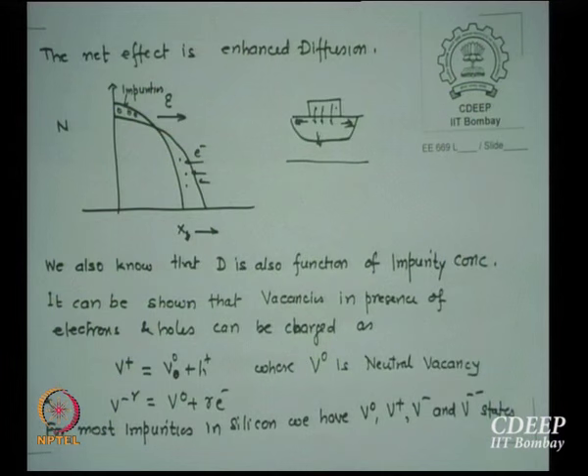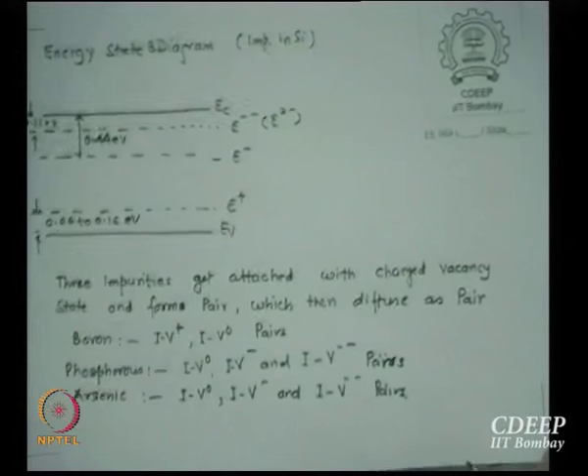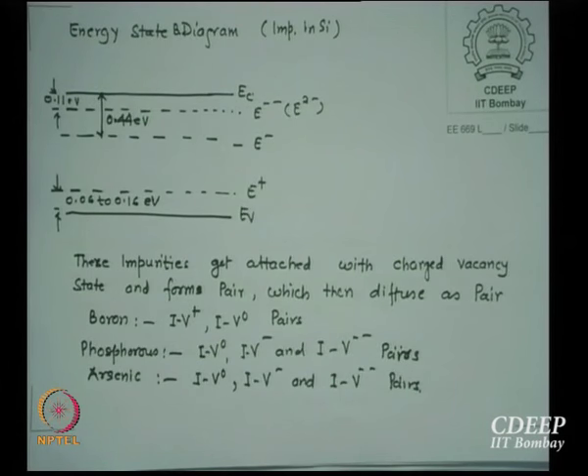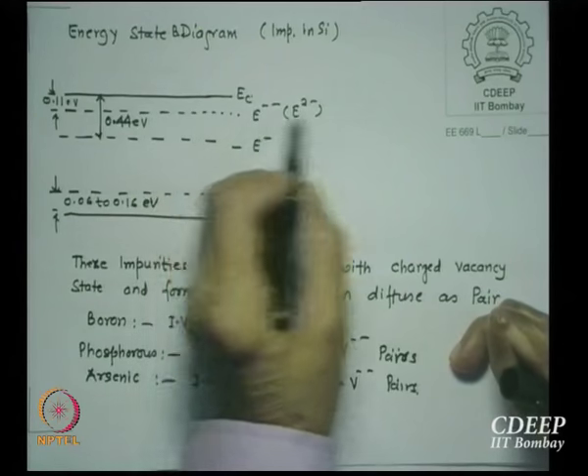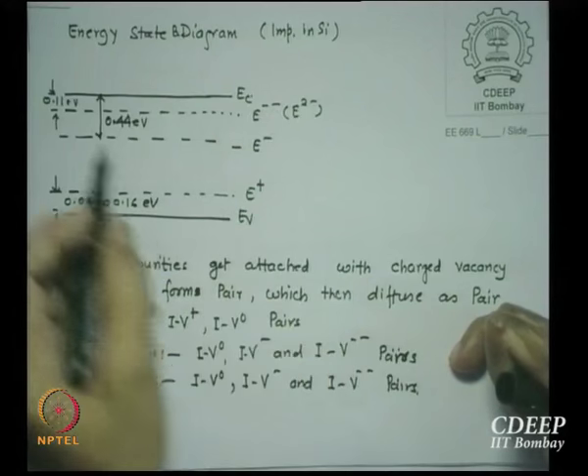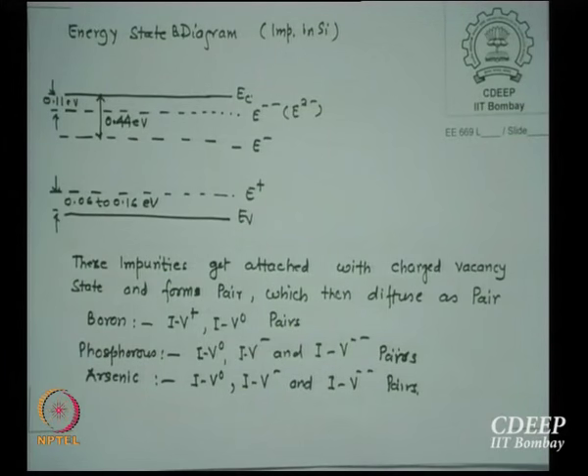Now, if there is a charged vacancy in the band gap of silicon, what does that mean? If these vacancies have their energy state in the band gap, then we have worries. If they are outside, we may not be worried. Maybe in the conduction band above, who cares? However, when we did a lot of other experiments, Raman spectra and many others, it was found that, particularly for impurities in silicon, there are two electron states, vacancy state V minus and V minus minus, which are energy E minus and E minus minus. The upper one is only 0.11 eV from the conduction band, the other is 0.44 eV.